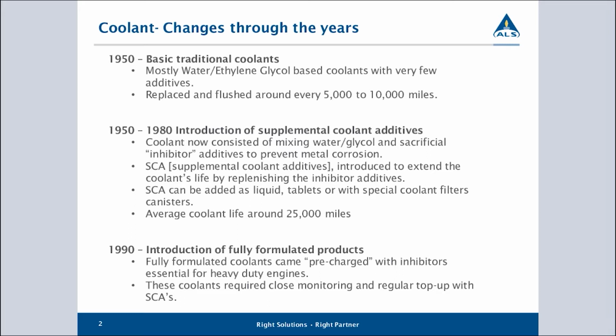So as it became apparent that just having water running in the engine would lead to corrosion, developments of coolants started to happen. Probably the first real coolant started to arrive in about 1950. And these would be water glycol mixtures that would contain some sort of inhibitor additive to try and stop corrosion from taking place. And the evolution started to move quite rapidly from then. What we had made were what we would now refer to as conventional coolants. Conventional coolants are coolants that contain an inhibitor additive that works by trying to prevent oxygen from coming into contact with the metal surface.